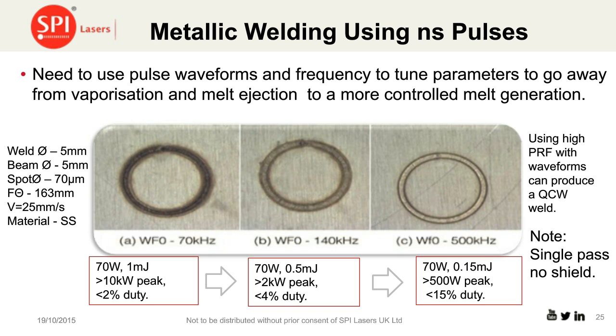And that's the kind of end output that you get. What happens is, as you increase the frequency, you reduce the pulse energy, you reduce the peak power, you maintain the average power, and the duty cycle starts picking up. And slowly what you'll see is that you move away from this melt ejection and heavy oxidation to something that's more attuned to a weld. And lo and behold, if you move up one step further to 500 kilohertz, where we've dumbed down effectively the peak power to just over 500 watts, and we're only using 150 microjoules, and we're talking about 15% duty cycle, we can create something that looks like a weld. What's interesting about this is that there is no shield gas, and it is done in a single pass.